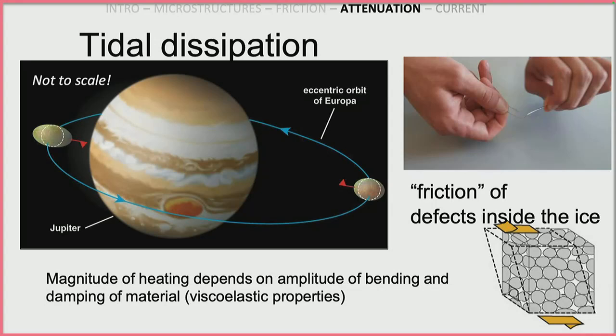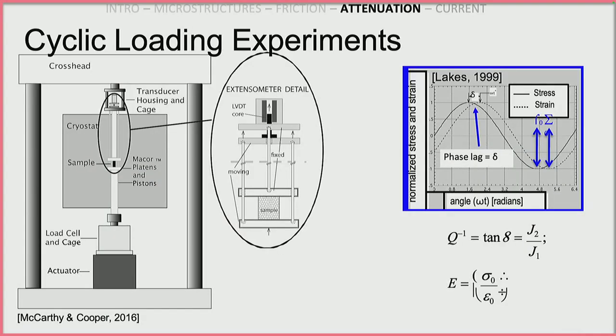So how do we measure this in the lab, though? We take an apparatus. Some studies have done this torsionally, but I've always been involved in this direction, which is you apply a uniaxial stress, a sinusoid of stress, to the sample, really small. We call it tickling. Really small stress, and then you measure the strain, which is also periodic. And if they were exactly in phase, that would be a perfectly elastic material, which doesn't exist. All real materials have some phase lag. The bigger the lag, the more squishy, attenuating the material.